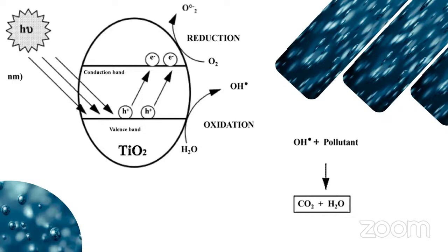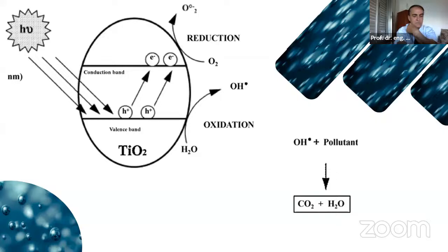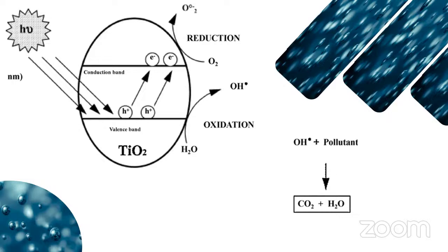Under UV light, the photons hit the TiO2, and the electrons are excited from the valence band to the conduction band. Definitely, the energy of the UV photon should be greater than the band gap of the TiO2. When the electrons are excited, the H+ hole that is left in the valence band reacts with hydroxide ions to produce hydroxyl radicals. These hydroxyl radicals react in turn with the organic pollutants and degrade them into carbon dioxide and H2O.